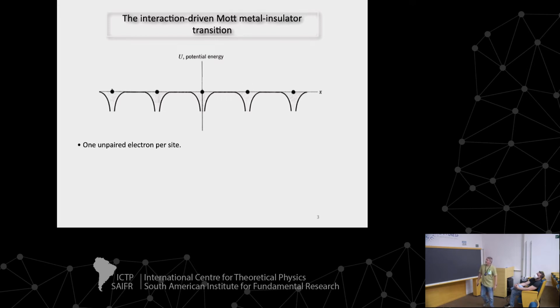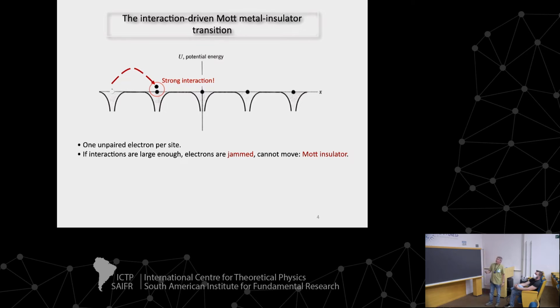The physics, as I said, is due to interactions. So the first condition for you to have this transition is to have one unpaired electron per site. Okay, so if there were no interactions, this would correspond to a half-filled band, and this would be a metal. But because of interactions, if they are strong enough, the electrons will be unable to hop from one site to the other. They will be jammed in their own sites, and this is going to give rise to an insulator, which we call a Mott insulator. So that's the basic physics of this phase transition.